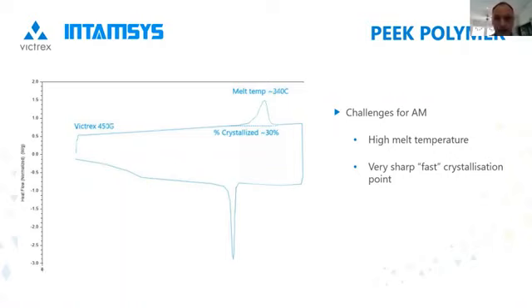The PEEK materials are engineered for melt processes such as injection molding, where the whole material is melted at this 343, but residence times and cycle times in injection molding are typically quite short. So the polymer is not held for long at these temperatures above the melt, and it doesn't get time to degrade. And the whole setup is typically within a closed system, not subjected to oxidation, which can also cause polymer degradation. So on the lower part of the trace, you can see the rapid peak of recrystallization at 297, and then this gives PEEK its characteristic 30% semi-crystalline properties, the chemical resistance and high strength.